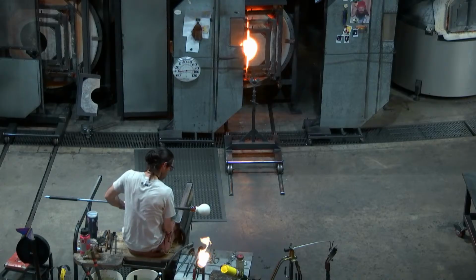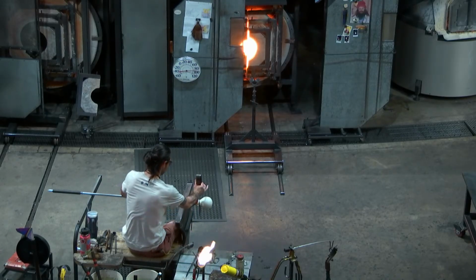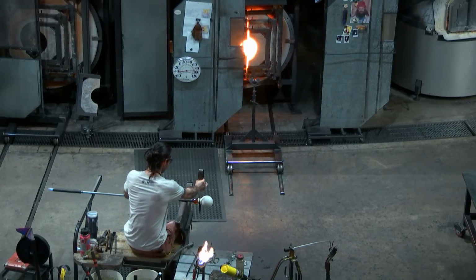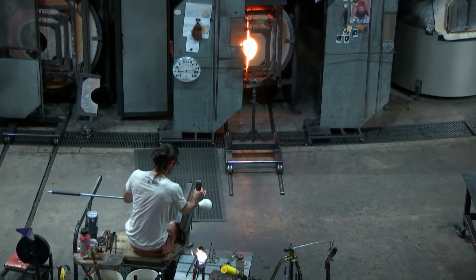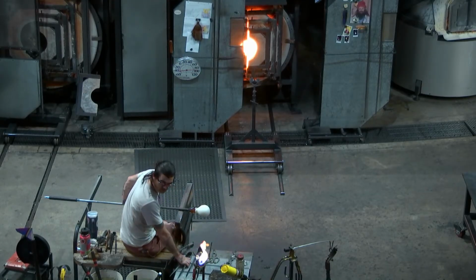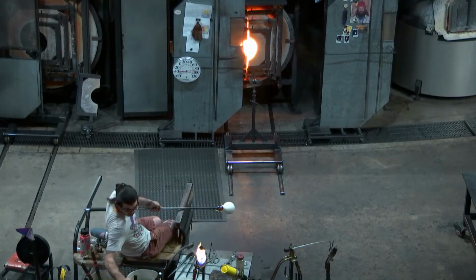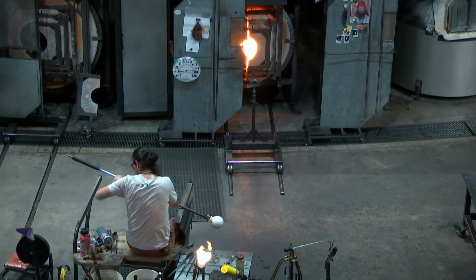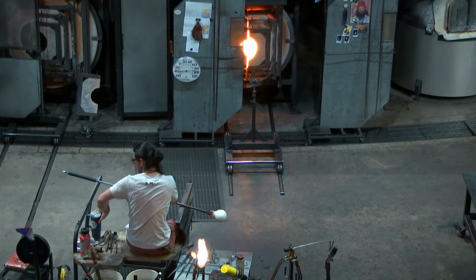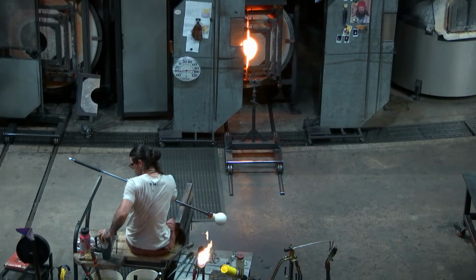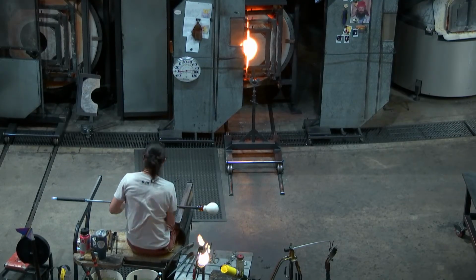We break it by using thermal shock to our advantage. If the glass gets too cold and you put water on it, it'll crack. So they put water on that specific spot. It makes a weak spot. That way they can break it off the pipe and it breaks exactly where they tell it to, instead of on whatever spot the glass wants to break.